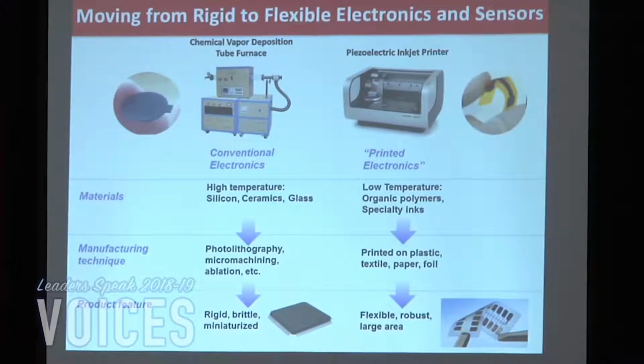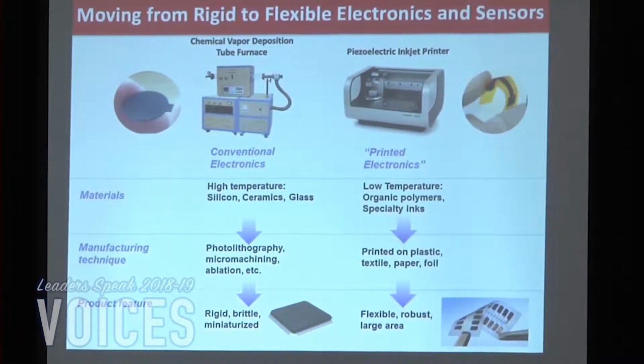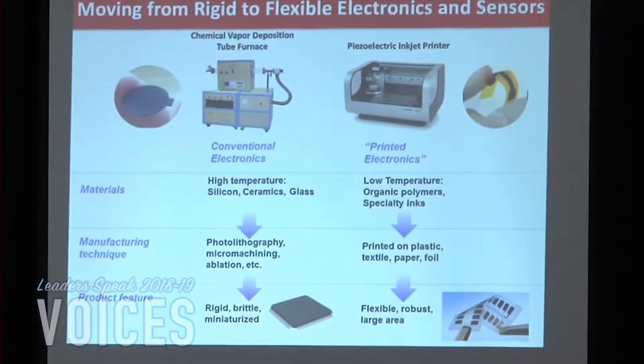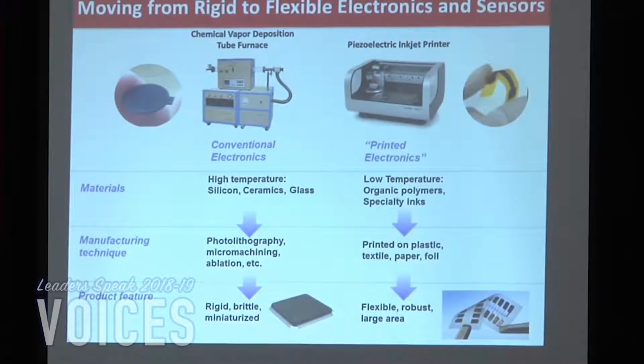When I was doing my PhD, I used to grow these nanomaterials, carbon nanotubes and graphene. If you think of the monolayer, a single layer of carbon is graphene in a 2D sheet or a plane. You roll that up into a tube, that's a carbon nanotube. If you have multiple layers rolled up into a tube, that's a multiwall carbon nanotube. So they're made very similarly. All these nanomaterials are typically grown in a chemical vapor deposition tube furnace.